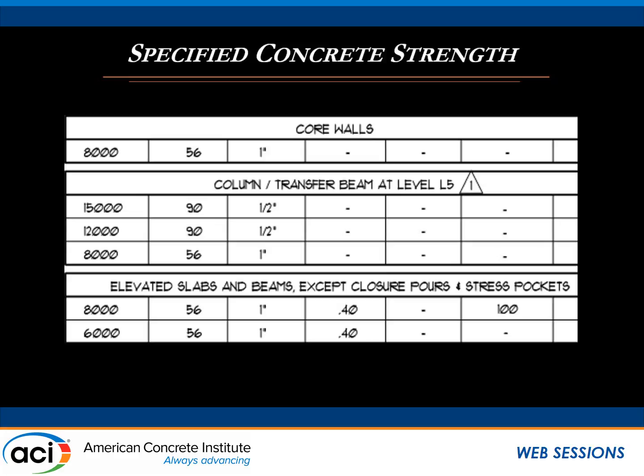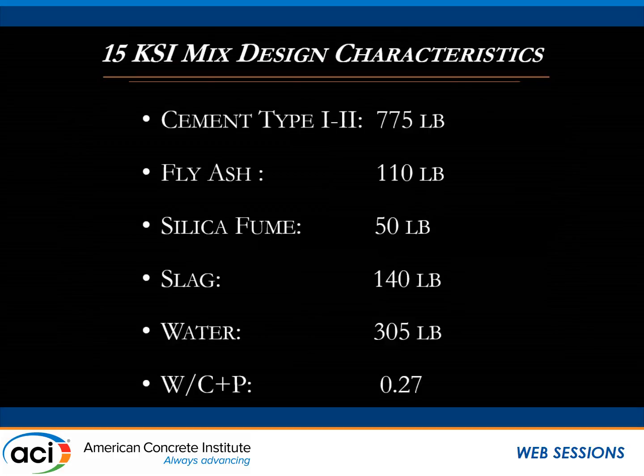However, a lot of engineers stop at that requirement, but if you keep on reading through it, you can use 75% of the strength of the column and 35% of the slab. So in reality, we needed about 14,000, but because of that sandwich in the slab, we used 15,000 in the column that equated to 8,000 in the slab, which is a more economical approach, since the column volume, cubic yards, is much less than the slab's.